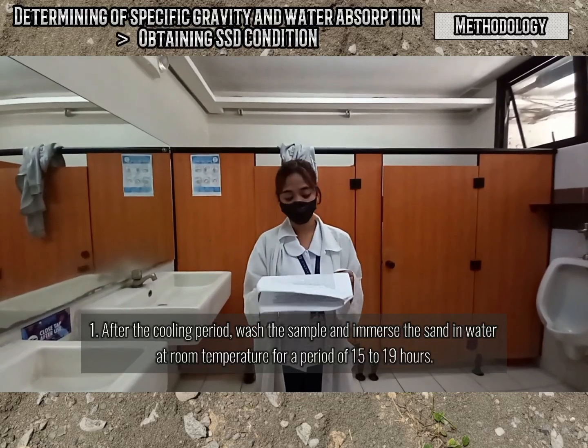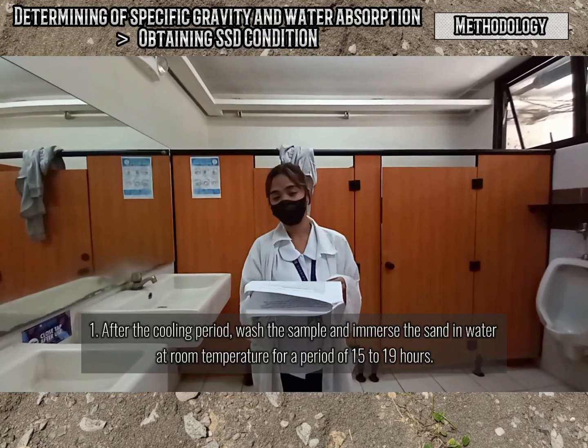After the cooling period, immerse the sand in water at room temperature for a period of 15 to 19 hours.